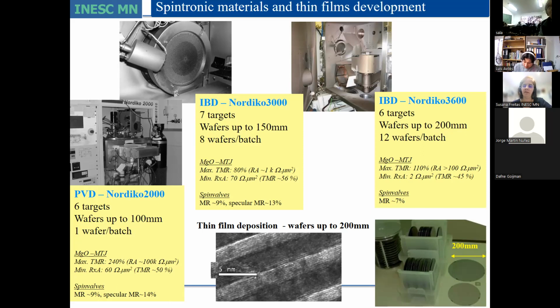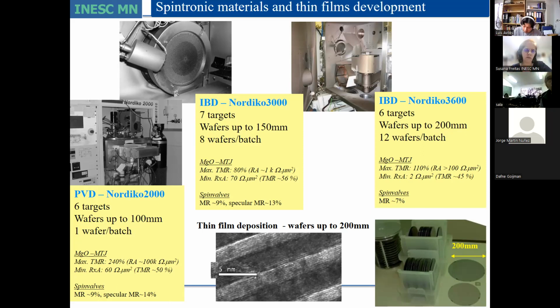For these tools the vacuum is low 10 to minus 8 torr. So it's not as low as MBE, for example, but it's okay for MgO. 10 to minus 8 is sufficient. The critical part here is cross contamination. In sputtering tools, the targets get eroded. As soon as you start using a target, the profile changes and the deposition rate changes with time. So this is a problem if you want to deposit, for example, the multilayers for tunnel junctions.